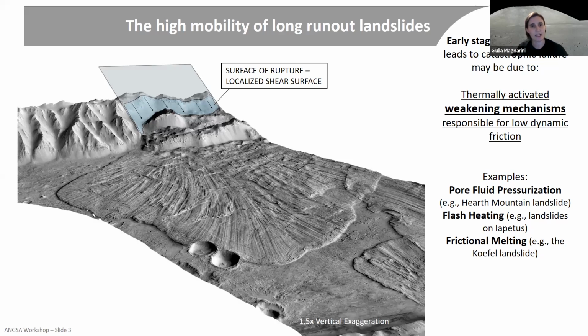But regardless of the emplacement mechanism, it is thought that the localized shear stress in a narrow slip zone leads to the development of high frictional heating that then triggers a series of chemical and physical reactions that are then responsible for the development of friction weakening mechanisms. And so at the beginning, we have the acceleration that is driven by gravity. And then it is further and rapidly promoted by a series of velocity weakening mechanisms that also lead to strength loss and to the development of high velocity already in the early stages of this catastrophic mass wasting event.